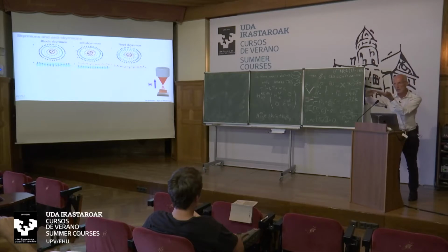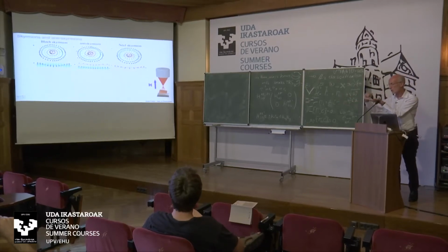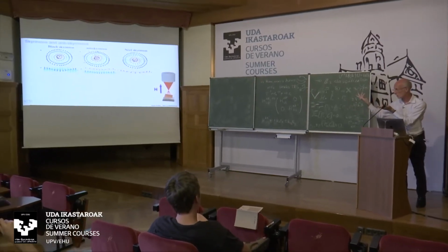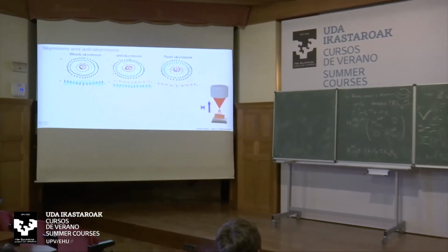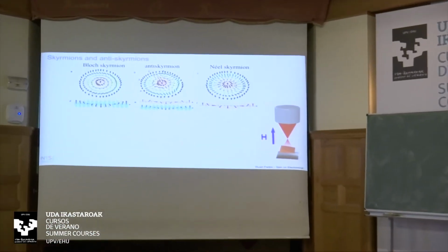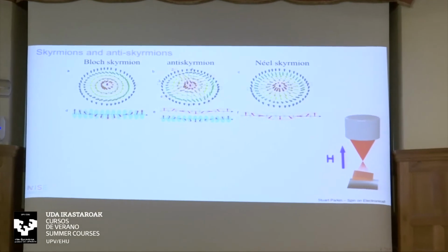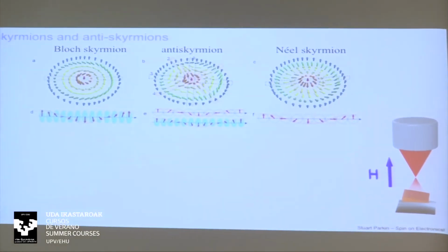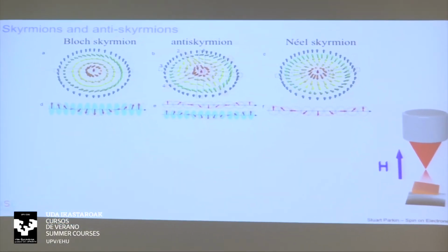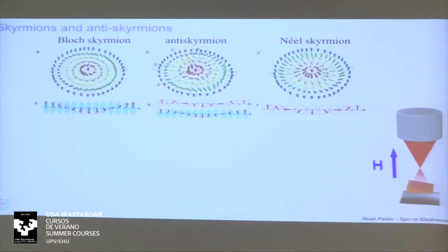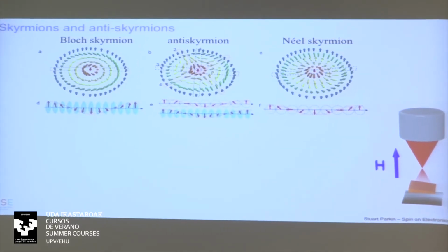So we have a lamella of this magnetic material. It's sufficiently thin that this 300,000 volt beam of electrons can pass completely through it. And as they pass through it, they feel Lorentz forces from any magnetic moment directing in the plane of this lamella.